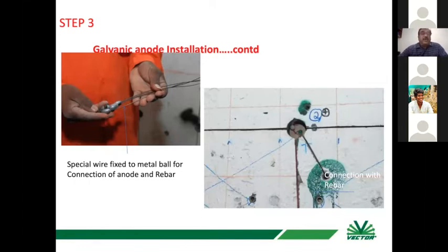We use a special steel connector so that the steel is connected to the anode, and the anodes are also connected to the steel with a special button connector, so that the joint of the wire does not get oxidized over a period of time, and the connection is proper for 25 years. This is what we want. So we take care of every small thing: a proper connector for the steel connection, then a gel-type button, and the anodes without cutting any steel, and then it is sealed with the mortar.